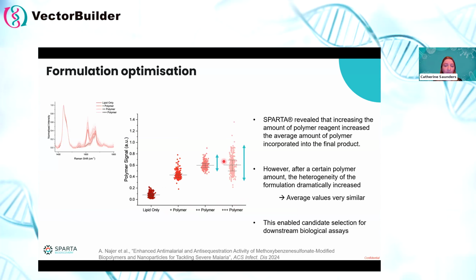And this is what you'd get from the bulk techniques. However, when we're looking at the single particle information, the individual dots, we can see that even though the averages are the same for these last two formulations, there's quite a big difference in the sample quality. There's a much higher spread in this final, highest formulation compared to the other one.